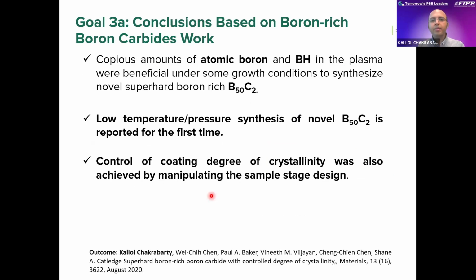This is the summary from the B50C2 work. The copious amount of atomic boron and BH in our plasma were beneficial under some growth conditions to synthesize the novel superhard boron-rich B50C2. Low temperature pressure synthesis of this novel B50C2 was reported for the first time in the literature from our group, and control of the degree of crystallinity was also achieved by simply manipulating the sample stage design.